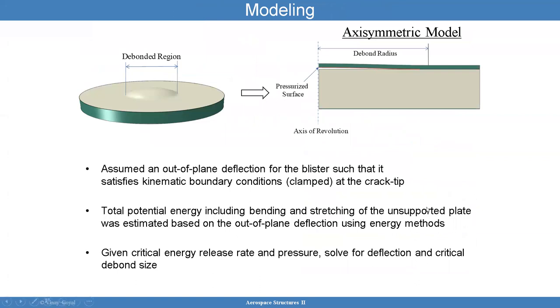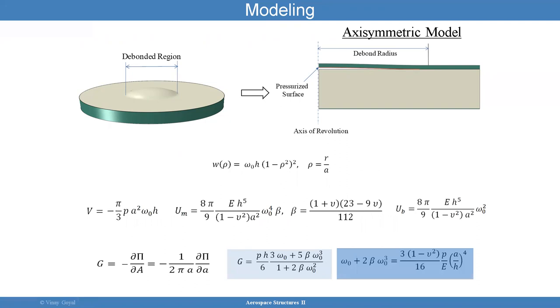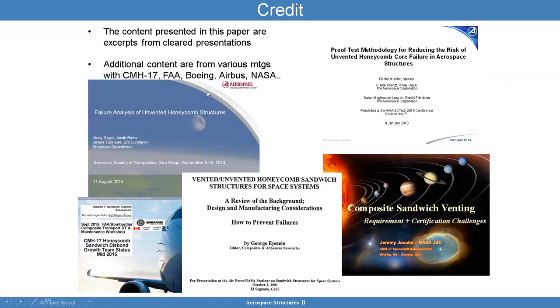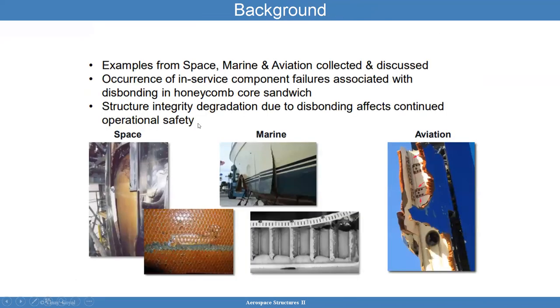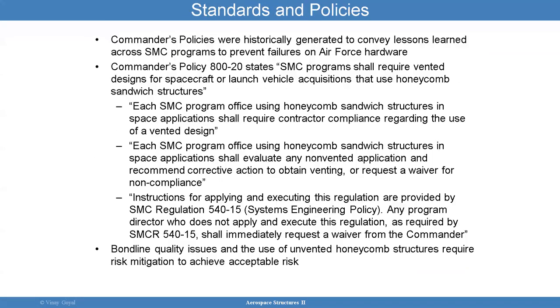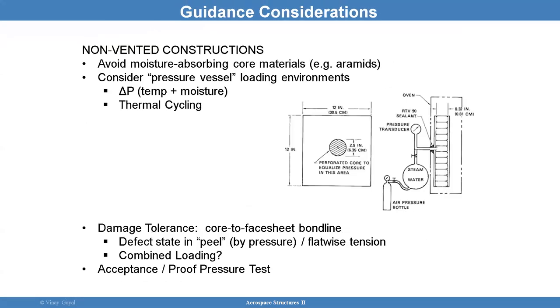For modeling, one approach is to create a disbond model. An axisymmetric model is one possibility — you put the core properties here and the face sheet properties there. For different pressures and compression loads, you want to calculate the energy release rate. I wrote a paper for the American Society of Composites that I invite you to download — it provides closed-form solutions that can be used in lieu of finite elements for pressure alone as a loading environment.